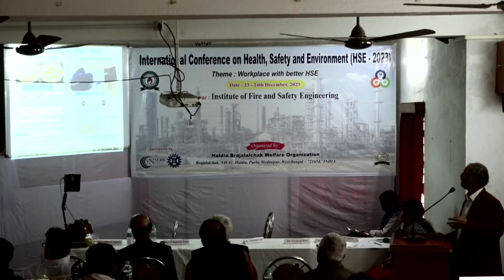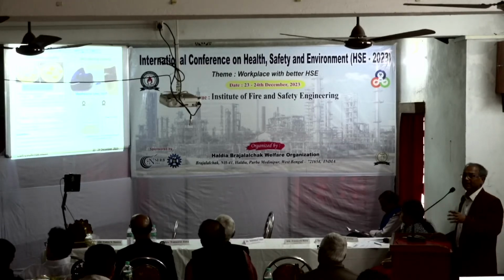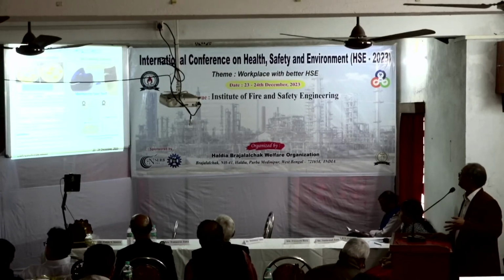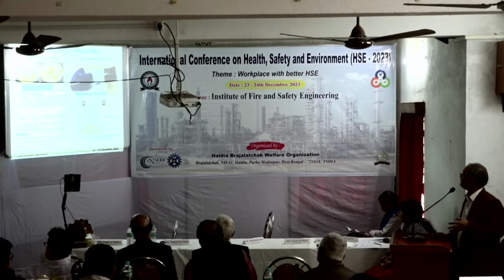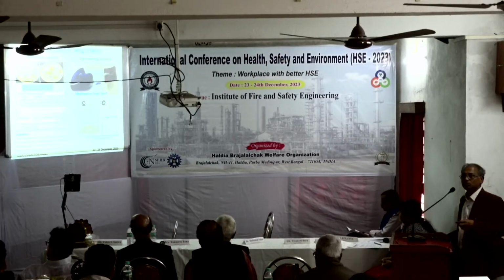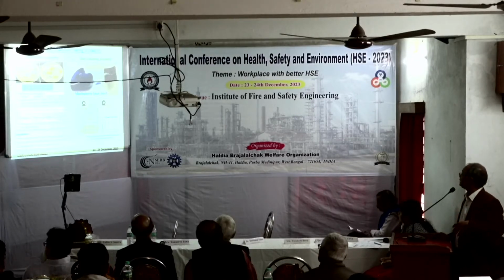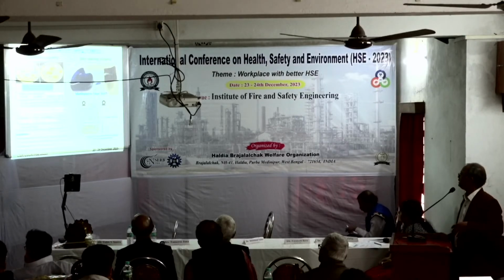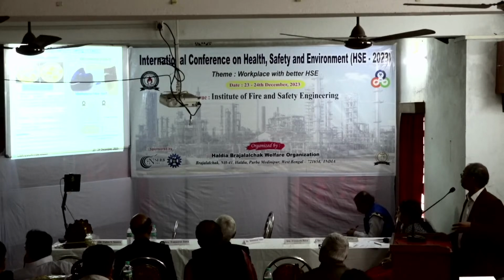When light falls, free electrons are generated, and combining with oxygen or water, they can produce radicals, that is OOH dot or O2 minus dot, and these are the precursors to kill the bacteria, to kill the microbes, and can act as an antibacterial coating. And the self-cleaning property we tested by using methylene blue as a dust, and we fabricated 1 meter by 1 meter size cotton fabric or PPE fabric, and this is the contact angle, 160 degrees for cotton fabric and 152 degrees for PPE fabric,